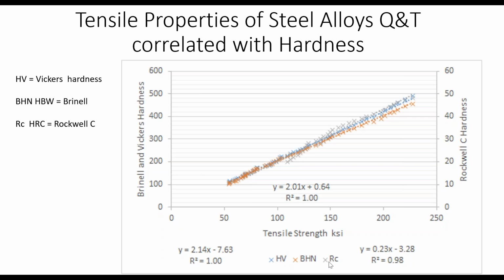Now, I put these nomenclature in. This is the handbook information for the correlation of tensile strength, UTS, with Brinell, Vickers hardness, and Rockwell C. So the little card you get from Wilson or the stuff you download from the web, that's what this is. This is not really any data. This is what you find in those little handouts. And if you look at this, you can see that you get R squareds that are close to 1 because it's really tightly correlated linearly. You can see that Vickers and Brinell are close to the same.